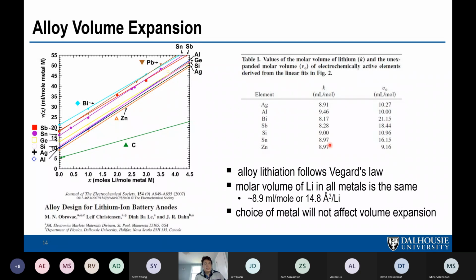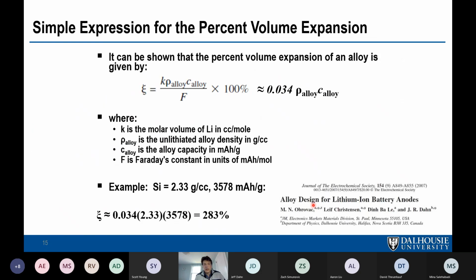This does make calculations of volumetric capacity a lot easier, because I know that when I insert one lithium into silicon, it's going to take up 14.8 angstroms cubed. And so that makes calculations easy. And that leads to expressions like this. So K is the slope of that line. And so you can calculate the percent volume expansion of any alloy using this equation, where the rho here is the density of the alloy as it's made before you put it in the cell. C is its specific capacity, and F is Faraday's constant.